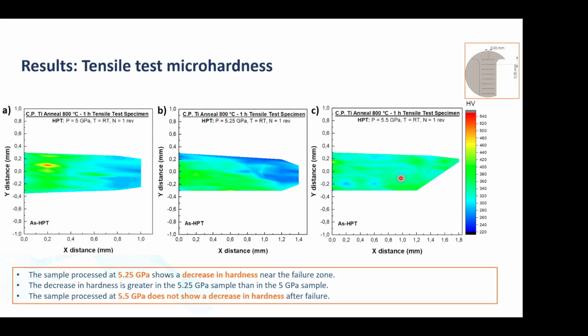What we did is we took fine hardness indentations along the tip of the failed tensile specimen, comparing samples at 5.25 and 5.5 gigapascals, and we see there's a hardness drop, especially in the 5.25, and that doesn't happen at 5.5. So something related to the stability of the omega phase is probably also a factor, so that it doesn't go back with the strain.